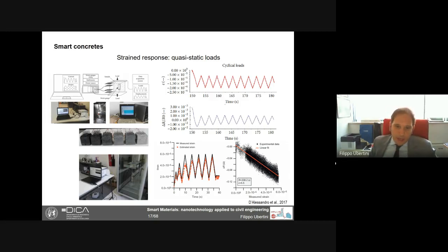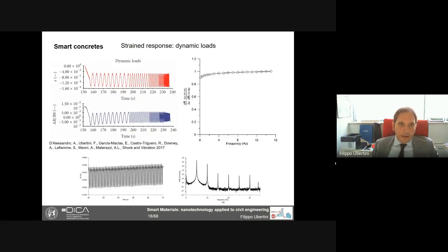If you compare this reading with what you get from strain gauges attached on the surfaces of the specimen, you get the comparison that you have in the bottom figure between the black line and the red dots, and you see there is a clearly linear relationship between change in resistance and strain.